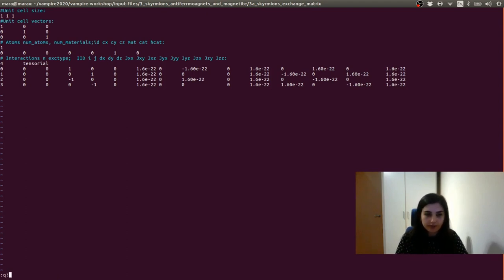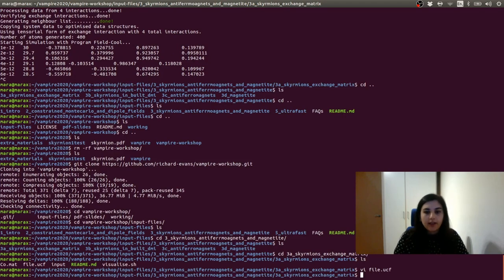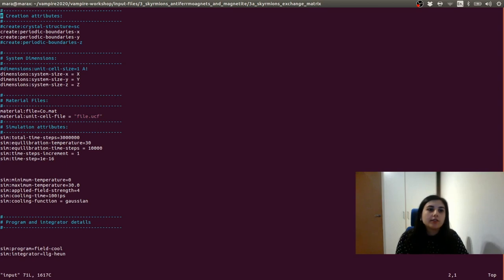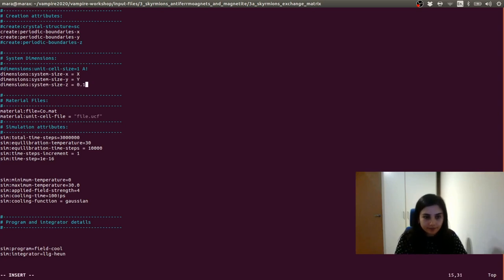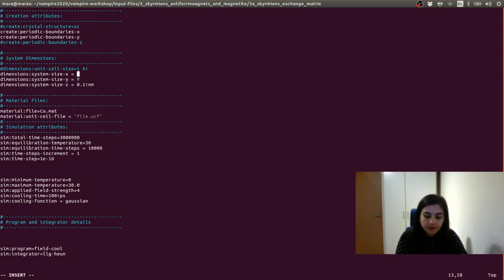So let's close the UCF file without saving it. In order to set up the rest of the simulation, we need to have a look at the parameters from the input file. We have a crystal structure of simple cubic because this is the way it is set up in the UCF file. We want to model a thin film monolayer, so we have periodic boundaries in X and Y, but not in Z. Let's set up the dimensions of the system. Because we want a monolayer, we need to set up the size of the system in Z as the size of our unit cell.